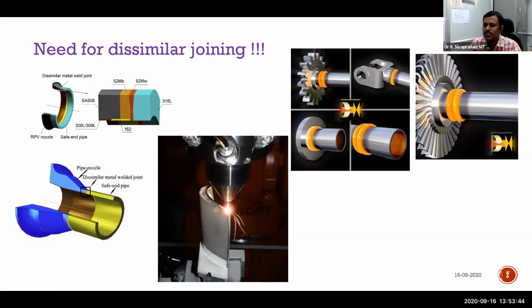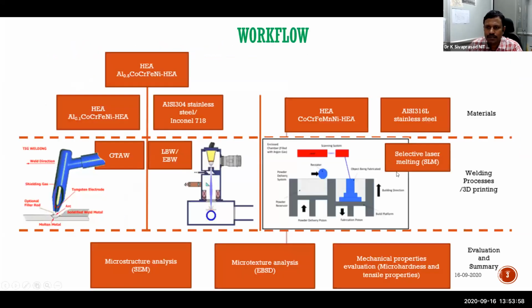The joint efficiency, joint strength, joint metallurgical properties, grain structure, phase structures, all these things one has to be very, very cautious about. One such attempt was made by my student, Mr. Soklingam. He himself made this workflow. I suggested that they take 2 welding processes and at least 1 or 2 additive manufacturing processes. We could not find 2 varieties of additive manufacturing, because we got a chance to work with selective laser melting, which is a powder bed fusion technique. We have GTA welding readily available in our lab, and we have good contacts with eminent people working in laser beam welding and electron beam welding in different sectors. So we took their help to get it done.